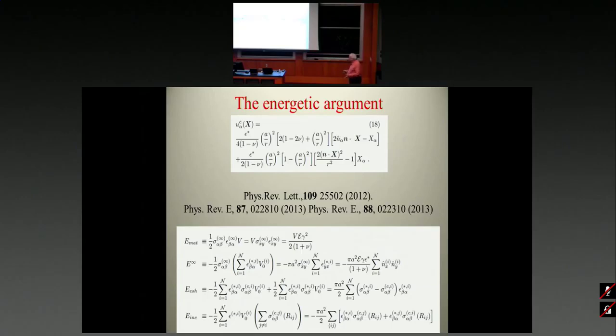So I started just to describe what are the objects that come in. Basically, it's the background elastic energy, the elastic energy of the background with the Eshelbys, the Eshelbys themselves, that is the sum over all of them of the stress versus strain, and the Eshelby interaction, epsilon of one on the sigma of the other, and so on. And now you take the whole thing and you say, let me minimize it, because I want to find the cheapest way to put n Eshelbys into a thing. And you find, amazingly, that the minimum is obtained when they're all sitting in line and with the same phase. So what I showed you here. So this minimizes, as the single one minimizes the energy associated with this loss of some stress locally, this minimizes the energy that it costs to do this globally.